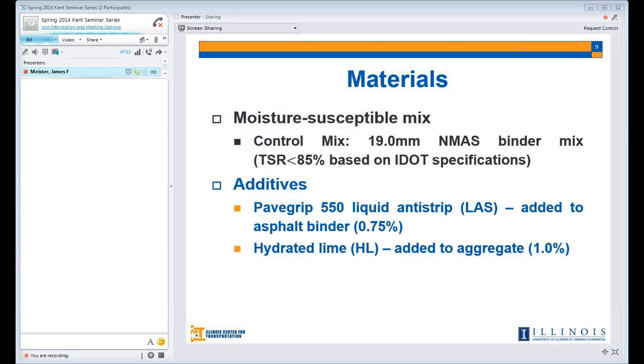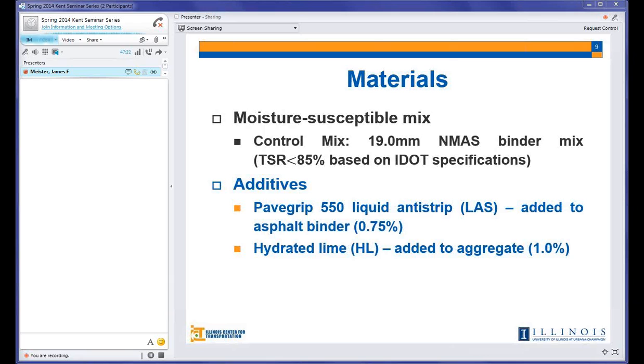Additives used: again, I forgot to mention that this mix is from District 5. The additive was a liquid anti-strip, brand name Pavegrip 550, and this is also used in District 5. So in District 5, when they need to add liquid anti-strip, they use this liquid anti-strip. And we used 0.75% by the weight of the binder. So the liquid anti-strip was added to the asphalt binder. For the lime, we added 1% lime to the aggregate, so 1% by the dry weight of the aggregate.